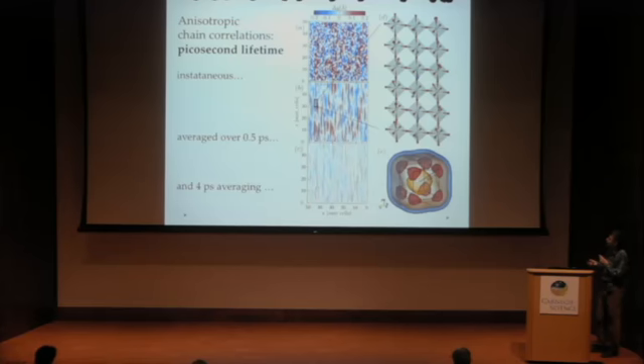So the calculation was done in a 50 times 50 times 50 box. We can make a cut through the simulation box, and each dot here, one of the 50 times 50, corresponds to one perovskite unit cell. What is shown here is an instantaneous snapshot of the configuration, and the color code is the displacement of titanium in the y direction, the vertical direction. So if you think about a small area, each dot is a perovskite lattice, so titanium, of course, is displaced in an arbitrary direction, but we look only at the y component, and this is color-coded.